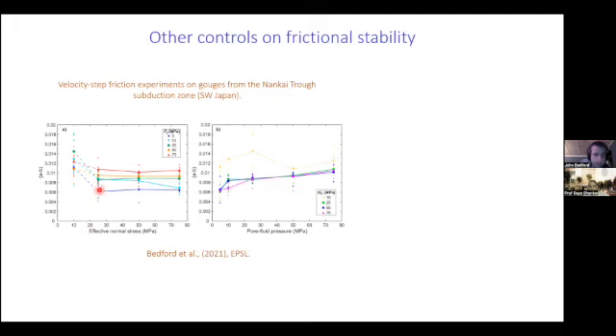So in this panel A on the left here, you can see that for a given pore fluid pressure, the A minus B value doesn't change much as you increase the effective normal stress. But at a given effective normal stress, if you increase the pore fluid pressure, then we found that A minus B actually increases. So the system essentially becomes more stable at higher pore fluid pressure. And the same data is just plotted here in panel B, where you can see we've got pore fluid pressure on the x-axis instead. And we've got this increase in A minus B with increasing pore fluid pressure again.